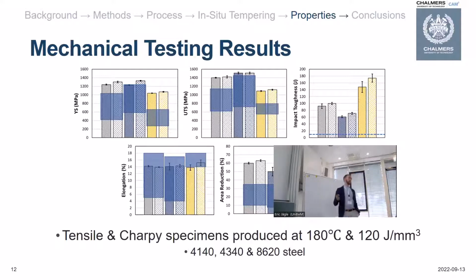And so we conducted mechanical property testing for the low alloy steels that I mentioned, and we just produced them at the highest preheating temperature because that gave us the most stable processing range. And we also tested them in orientations vertical and horizontal to your building platform. Okay, so that's out of the way now, and I can talk about all these bar charts and what they mean.